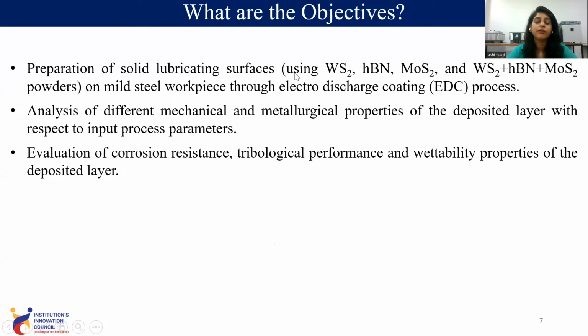So what are our objectives? It means what we are doing. By studying the research gap, we have seen that there is no soft powder use that I've already discussed with you. So in this process, we are using the solid lubricant coating. That is the solid lubricant WS2, hBN, MoS2, that is, molybdenum disulfide, tungsten disulfide, and hBN. So we are using these powders to improve the characteristics of the mild steel surface through electrical discharge coating process.